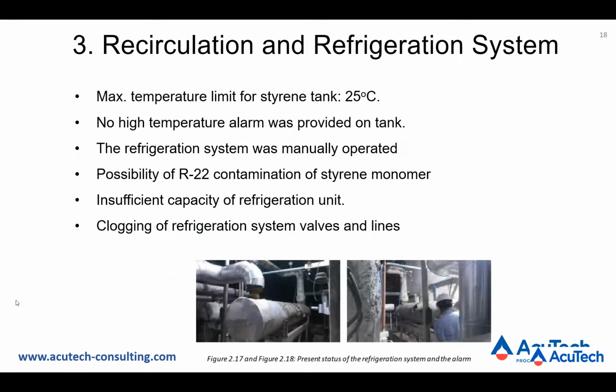Apart from the cooling methodology, there were issues with respect to the recirculation refrigerant system. The preferred storage temperature is in the range of around 10 to 18 degrees centigrade with upper limit of 25 degrees centigrade. If the temperature approaches 20 degrees centigrade, the tank contents must be cooled. It was revealed that there was no high temperature alarm on the tank.